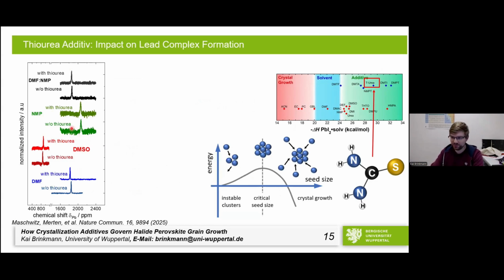And this is where the frustration began. Having a look at different solvents here, you always see the peak that we see in lead NMR, so basically you see the environment of the lead. We put the additive in there. According to the Lewis base activity, it should have a huge tendency to coordinate with lead, and the lead didn't change. Not at all, no matter what we did. We did DMF, NMP, DMSO, so solvents that are highly coordinating, less highly coordinating, mixtures of solvents, and all of them gave us almost identical signals.